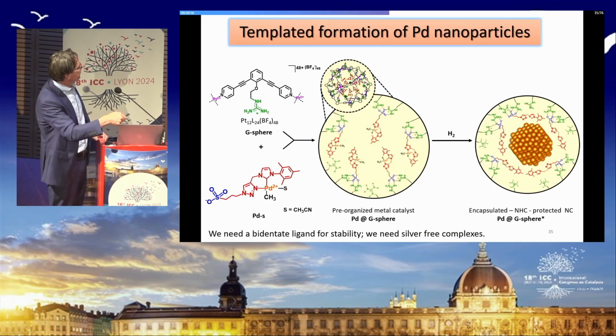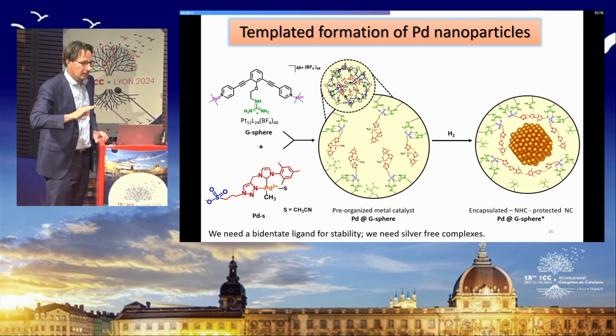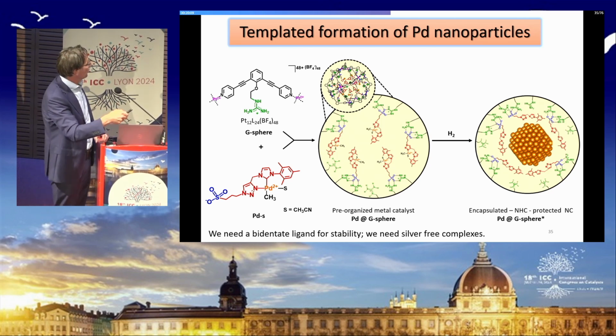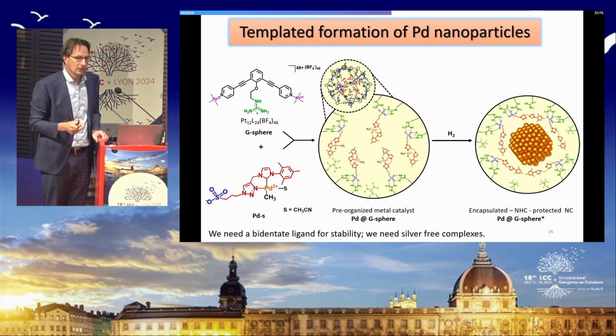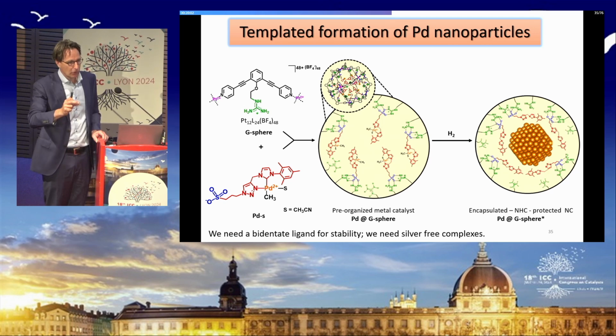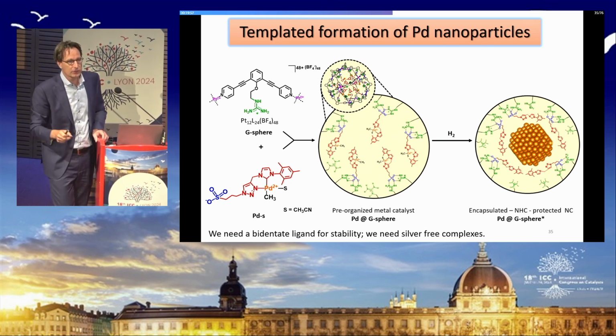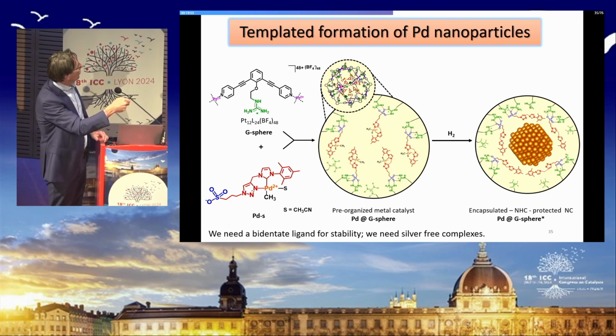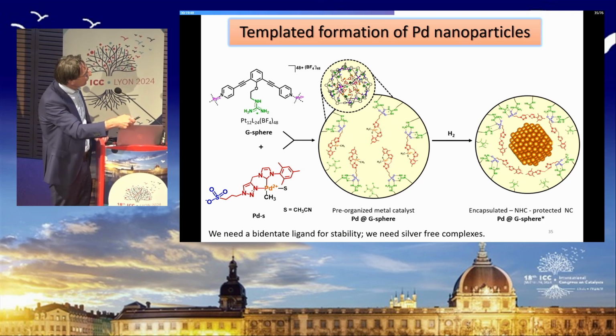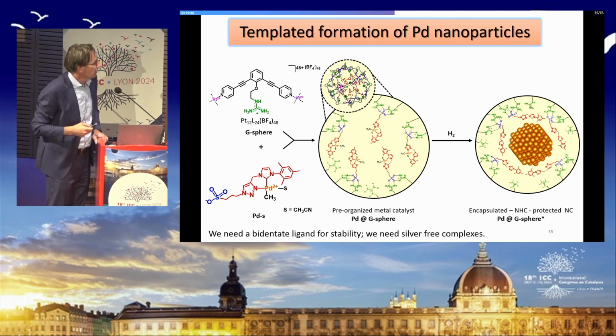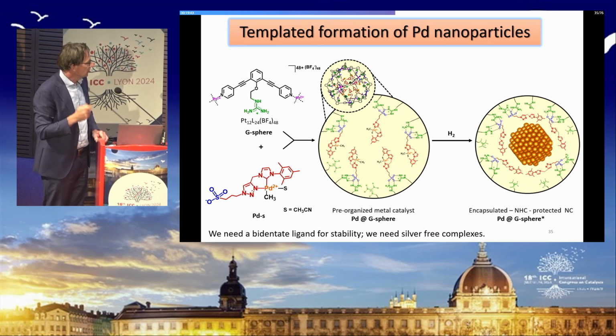So the next step was moving towards palladium, and if we want to go to palladium, we explored a lot of different carbene complexes, and we found that we really need bidentate ligated palladium complexes to have an optimum between the stability of the palladium complex, but also reactivity towards hydrogen. So again, it's equipped with the sulfonate group, so it can be pre-organized in the cuboctahedral cage. And again, we need hydrogen for the reductive formation of these nanoparticles.